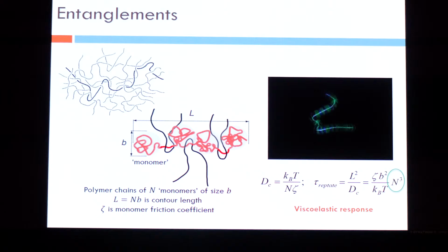What they do is they prevent each of these molecules from having large motions in directions which are orthogonal or transverse to the length of the polymer. And that is because the other entanglements are holding them. So these polymers can't move any which way they want. In particular, they can't move very easily perpendicular to the length of the polymer chain itself because they are constrained by the other polymer molecules. And these are called entanglements.